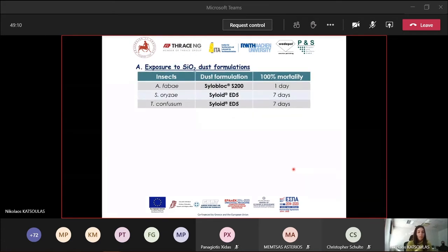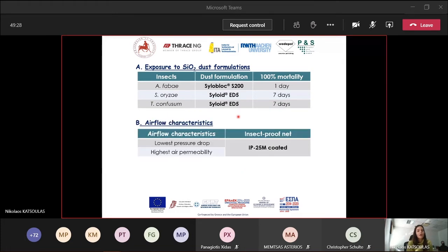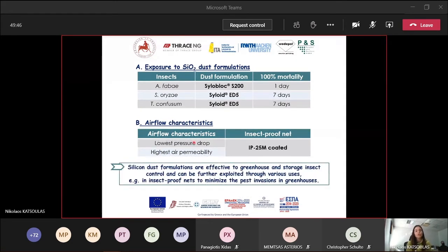So, to sum up, the most effective dust formulation against Aphis fabae proved to be Siloblock S200, while in the case of the stored product insects, the most effective dust formulation was Siloid ED5. Concerning the airflow characteristics, we showed that the 25 mesh coated net, the net with larger pores that is coated with silica nanoparticles, had the lowest pressure drop and the highest air permeability. To conclude, silica dust formulations are effective against greenhouse and stored product insects and can be further exploited through various uses, for example in insect-proof nets, in order to minimize the invasion of pests inside the greenhouse.